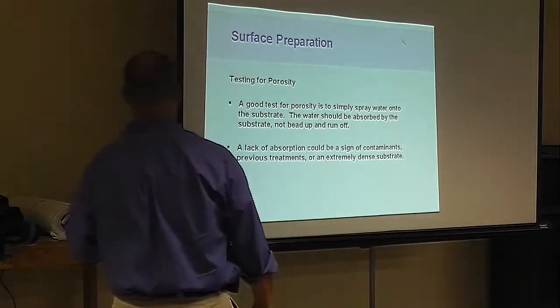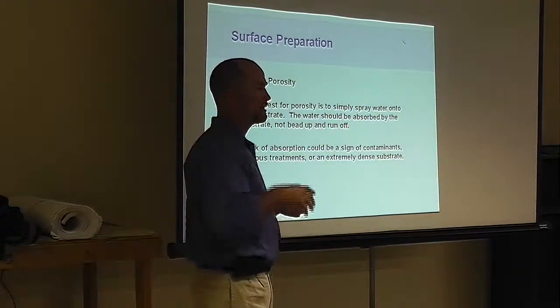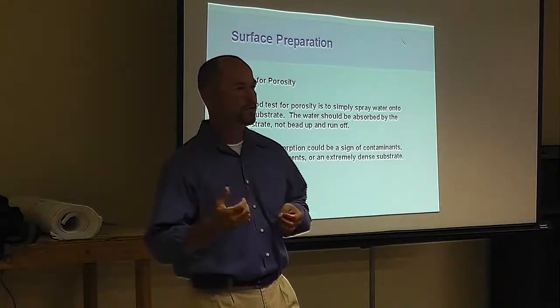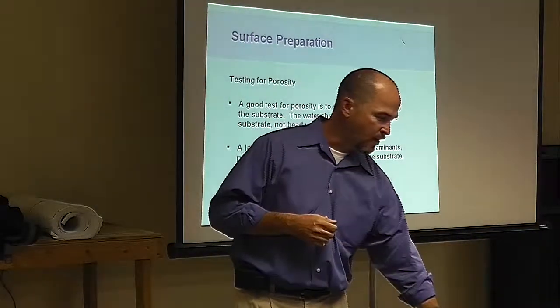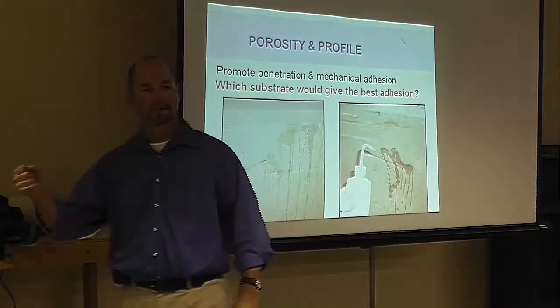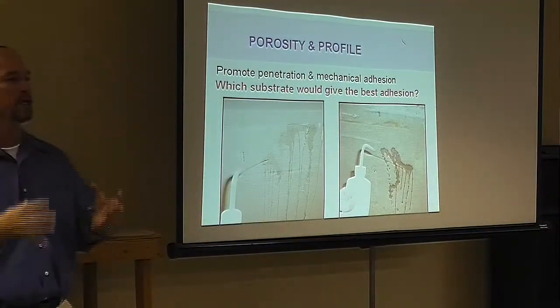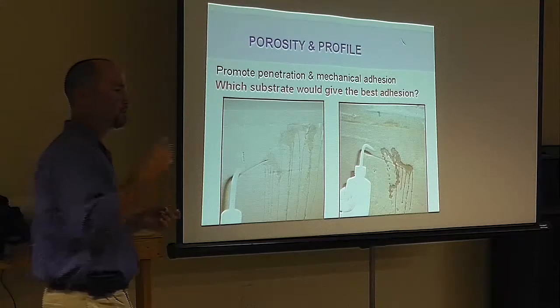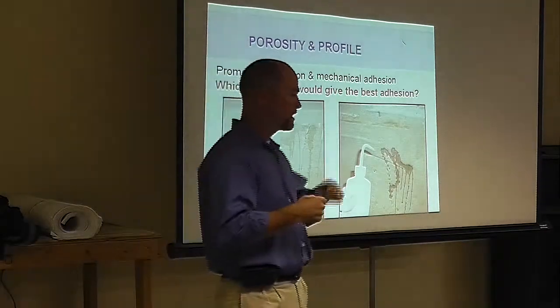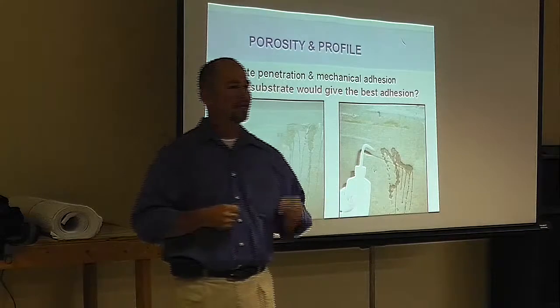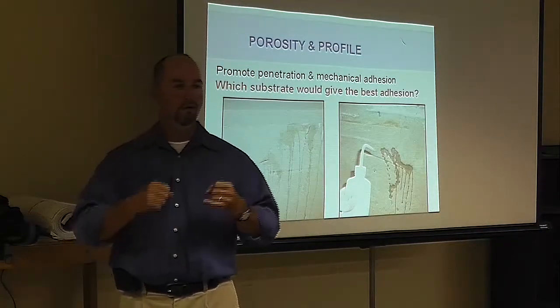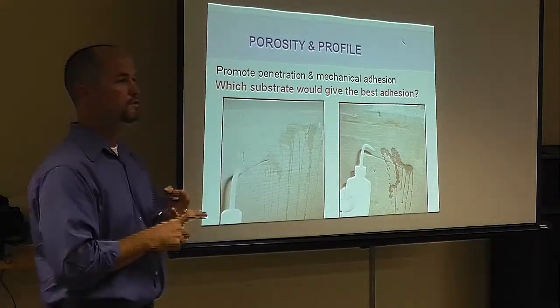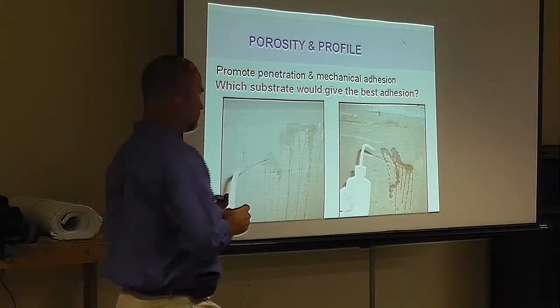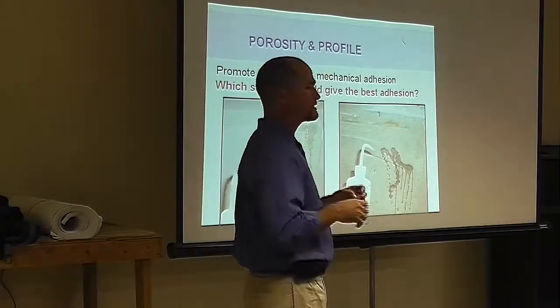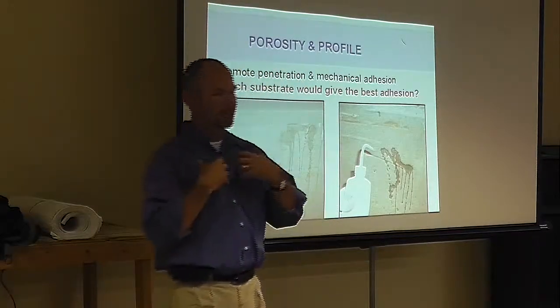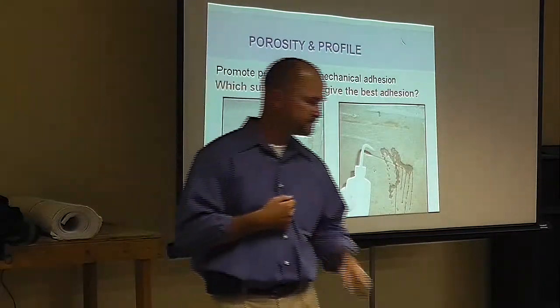One good test for porosity is that I carry around a squirt bottle. I go up to a substrate, especially if it's tilt wall new construction, and I'll wet that substrate. I want to see that moisture suck in. Same thing I do with deck coatings. When a guy's prepped that substrate for deck coating, I'll put water down, and I want to see it soak in. If I see that water bead up or not penetrate, you know you're going to have issues with the coating bonding to it. It's a quick, easy test to make sure you've got good adhesion. You want that to wick in so it can accept that coating.